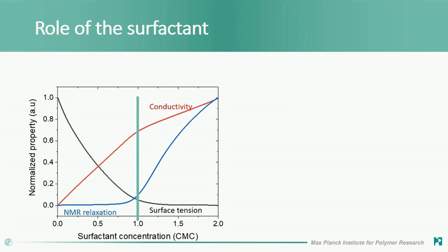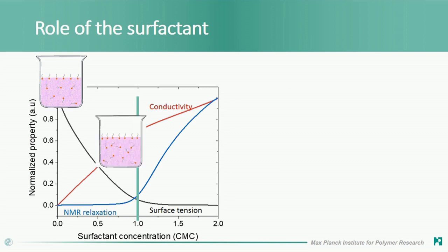If you probe the surfactant molecule itself by NMR spectroscopy, for example, the relaxation time will increase when you reach a critical concentration that is called the critical micellar concentration, where at this point, the surfactant molecules, so they are surface active, they really like to be at the interface between water and air, or between two liquids. If you slightly increase the concentration, you populate this interface a little bit more, but you have more and more surfactant molecules in solution, and at some point you reach a concentration where the interface is completely covered by surfactant molecules, and you start forming micelles inside the solution.